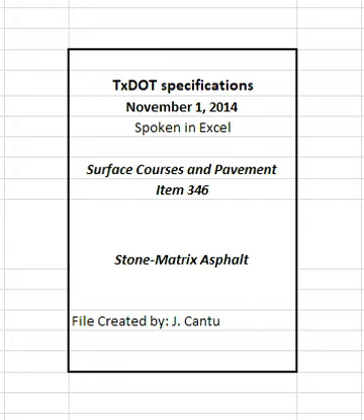Process the RAS by ambient grinding or granulating such that 100% of the particles pass the 3/8 inch sieve when tested in accordance with TEX 200F, Part I. Perform a sieve analysis on processed RAS material before extraction, or ignition, of the asphalt binder. Add sand meeting the requirements of Table 1 and Table 2 or fine RAP to RAS stockpiles if needed to keep the processed material workable. Any stockpile that contains RAS will be considered a RAS stockpile and be limited to no more than 5% of the HMA mixture in accordance with Table 4.